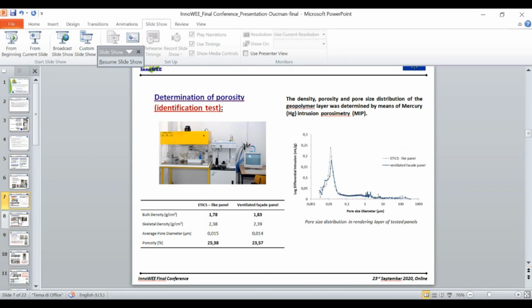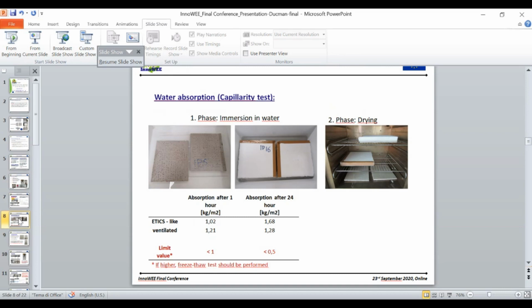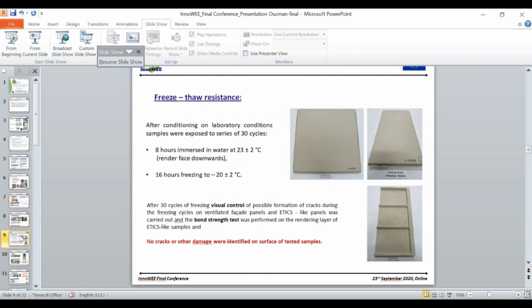So the next parameter, which is important for the facade use, is the water absorption test. The water absorption test also covers the same parameter as the previous test, which is porosity. In this way, it's determined through water absorption after 1 hour and after 24 hours. Here it's written in ETAG 004 that if the water capillary absorption is above 1 kilo per square meter after 24 hours, then the material needs to be tested for freezing, to see if it's resistant to freezing. In both cases of our ETICS-like and ventilated facades, these values were over what is prescribed for cement-like materials. So we decided that we will perform the freezing test.